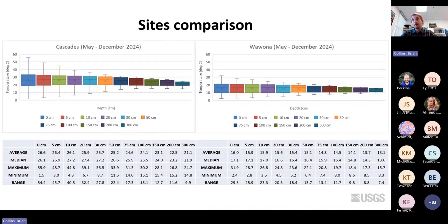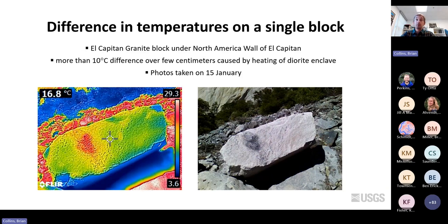While on the Wawona side, the north-facing one, the temperature range on the surface was only 30 degrees, with an average of 16 and a maximum of 32 degrees in summer. You can also see that the temperature at the 3 meters is about 10 degrees higher in the south-facing slope than in the north-facing slope. But obviously you can, of course, notice these differences also within one rock block.